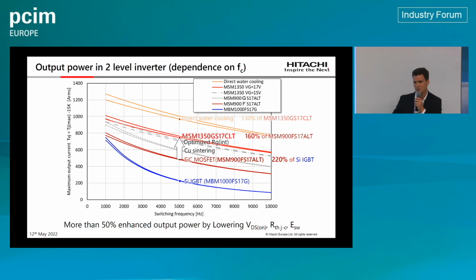Hence the 50% increase in the rated current, but actually you get a little bit for free. We'll give you a little bit more. If we were then to apply this direct water cooling, due to the reduced thermal impedance we can increase that a further 30% compared to this, even compared to this new product. And actually, if we compare it to the original MOSFET, it's sort of a 2.5 times increase in current.